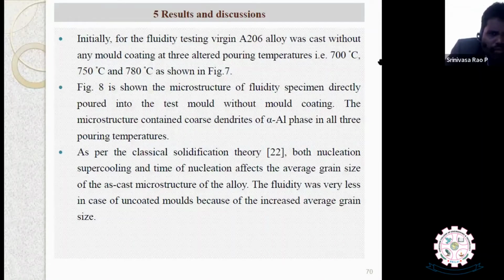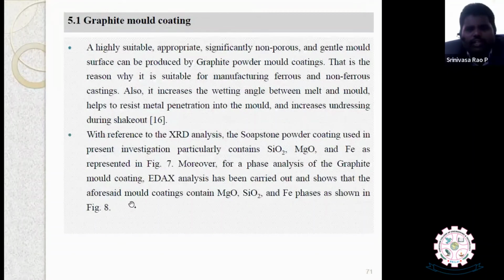Without mold coating, the pouring temperature is as shown before. Figure 8: microstructure of the fluid specimen directly poured into the test mold. Now graphite mold coating, let me explain. A highly suitable, significantly non-porous and smooth mold surface can be produced by graphite mold coatings. That is why it is suitable for manufacturing ferrous and non-ferrous castings also. What is the reason? It increases the wetting angle between the melt and mold, helps to resist metal penetration into the mold, and increases easy dressing during shakeout.